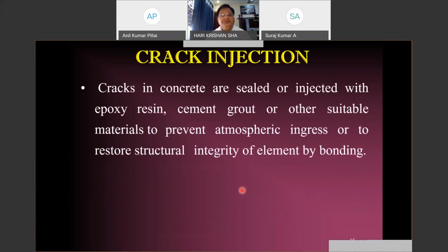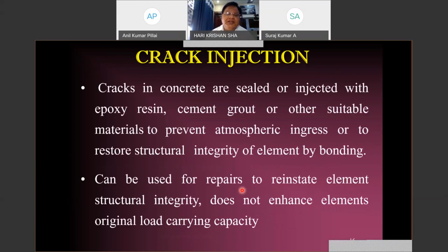Now, as far as the crack injection technology is concerned, this method I would not like to recommend. This is simply a cosmetic treatment, in the sense that the cracks in concrete are sealed or injected with epoxy resin, cement grout, or other suitable materials to prevent ingress of atmospheric gases or to restore structural integrity of the element by bonding only. So it can be used for repair, and it has nothing to do with the enhancement of the structural strength. It does not enhance the element's original load carrying capacity.